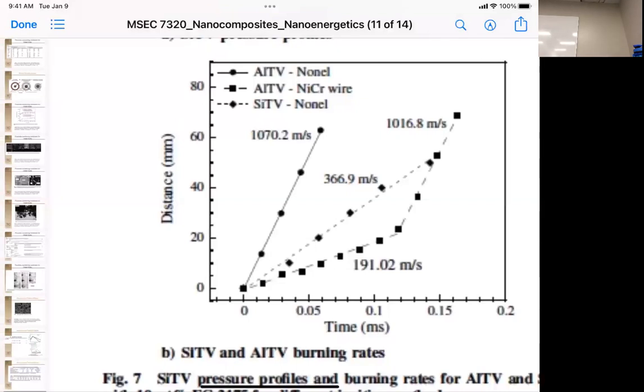Nickel is a better one. So we see a slightly lower slope. So that could be a good thing right here. This is more indicative of a propellant. This is getting really close to something that detonates, to close out. So by having that slower burn, you're actually going to be better as a propellant.